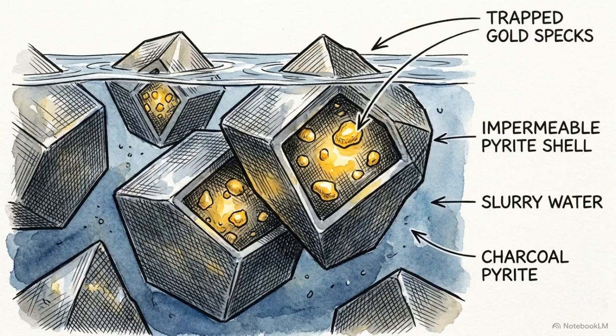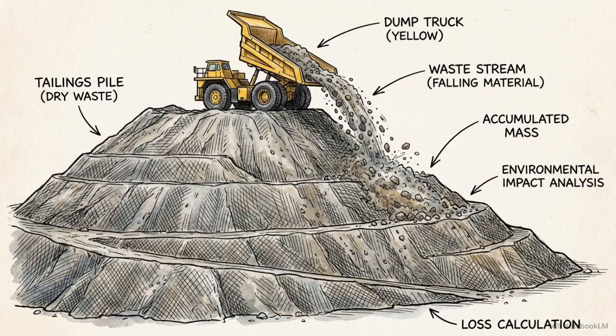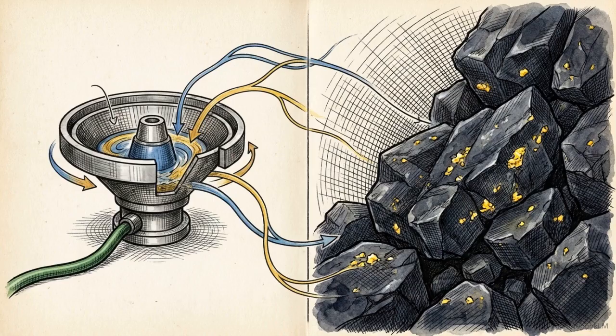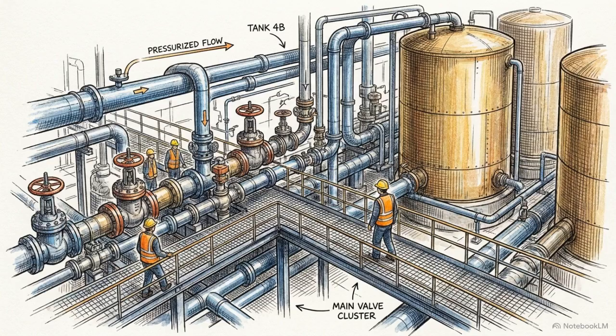The trade-off is that the centrifuge cannot catch the finest encapsulated particles, meaning up to 15% of the gold is lost to the tailings pile. Gravity separation illustrates that low operational costs come at the direct expense of maximum extraction potential. To capture the gold that gravity leaves behind, the next logical step is to increase operational complexity through flotation.